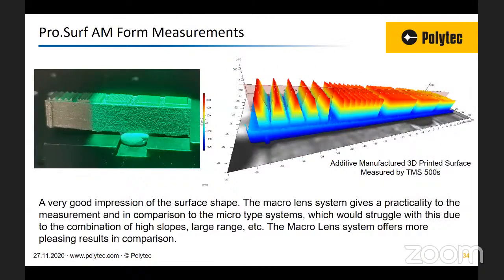For form measurements, here I have an additive manufactured surface, an artifact which has large triangular shapes on the surface. If you look at the scaling, the Z range is well over 1 millimeter. The practicality of measuring this with a microscope is not really ideal. Of course, the microscope will give you really good information close up, but if you want an overall view of the surface, then the macroscope could certainly do this in a much more practical way.